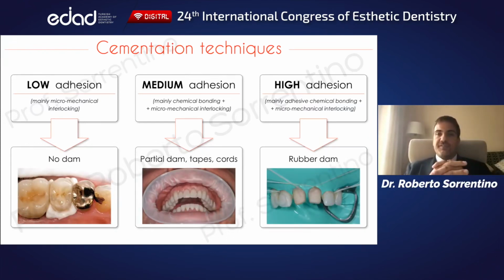Of course, different luting agents necessitate different isolation approaches. No dam is strictly needed for water-based materials. Moisture control by means of different isolation aids can be achieved for simplified adhesive systems, while the rubber dam should always be used with three-step total etch cements.